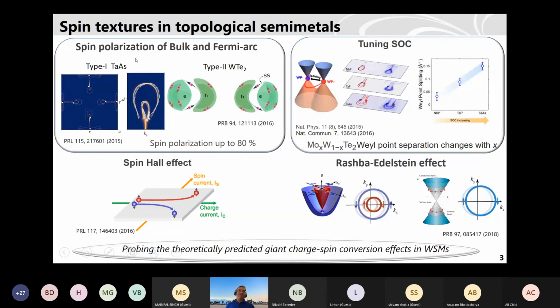As I told you, the spin polarization of the bulk and Fermi arc is quite interesting for tantalum arsenide and tungsten telluride. The tantalum arsenide results are already measured by ARPES, and tungsten telluride is also measured by ARPES, so this gives very nice properties. What is possible is that you can tune the spin orbit coupling so that you tune the separation between these Weyl nodes. This is one Weyl point, another Weyl point here, and there is a Fermi arc. You can change the separation by tuning the spin orbit coupling. From niobium phosphide to tantalum arsenide, you change the spin orbit coupling and you see the Weyl point splitting is also increasing. So these are very interesting systems to study.